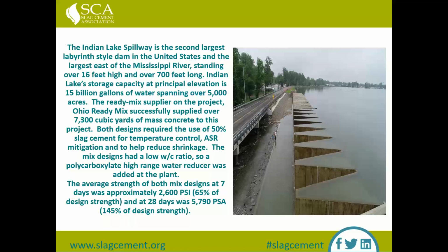The designs they used in this had a 50% slag substitution, and this was for 3 reasons: the first was temperature control for the mass concrete, ASR mitigation, and then also to help reduce shrinkage. So it had a very low water cement ratio and utilized a high range water reducer.